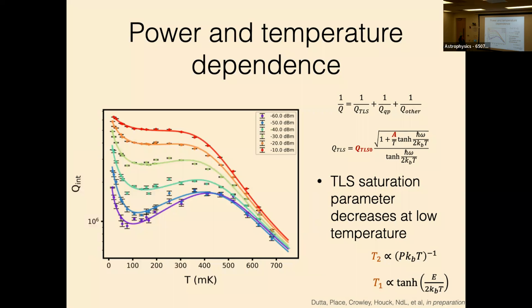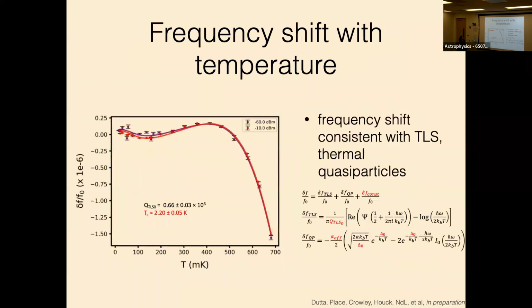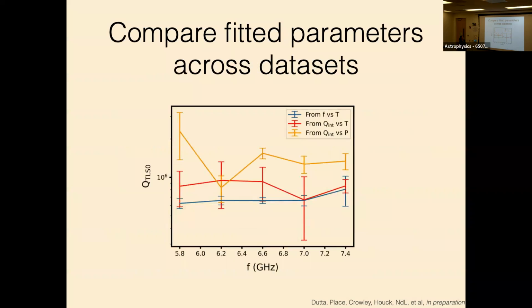And in doing so, the important thing here is that we can extract a parameter that appears to be robust and actually parametrizes the material losses. So now we have this kind of QTLS naught. We can do an independent measurement by looking at the frequency shift of the resonator with temperature and get out the same parameter. And then we can compare whether or not we get the same parameter if we do these 2 separate measurements. What you should look at is the red and the blue points, which are basically overlapping for all of these devices. Incidentally, yellow is what you get if you just do one of these power sweeps. So you overestimate the Q and it gives you the wrong number.